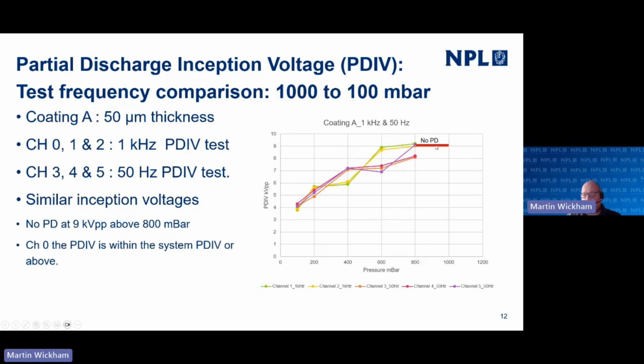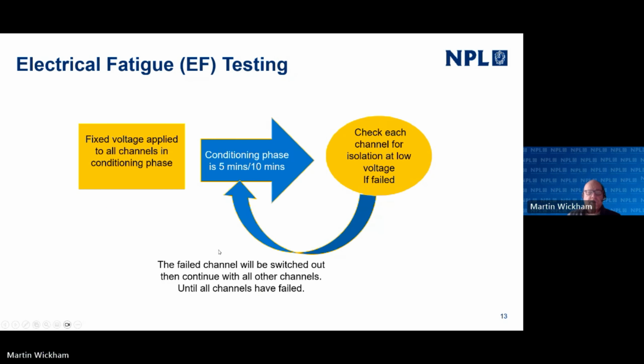Quite often you'll see these red lines appearing on the graph. That means that we could not detect PD at our maximum voltage, which at ambient is up towards 10 kV. So we couldn't see partial discharges with these samples at that voltage. But if we come down here at 100 millibar, you can see that we are down at 4 kVpp and below. So our system is essentially quite simple, but it's much more difficult to achieve this in practice.